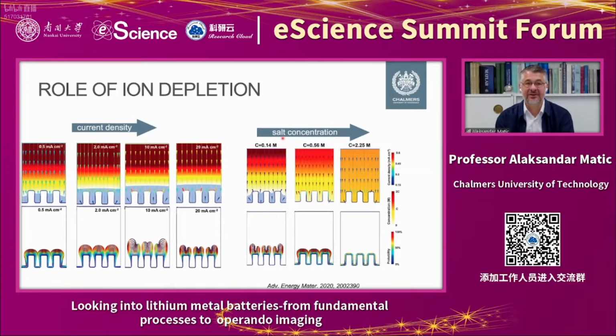The key here is what happens in a cell when you run, for instance, a large current or low temperature, basically when you have a transport limitation in a system: you get a depletion of lithium ions close to the surface. And if you have a depletion, then you will have preferential deposition on any protrusion that is formed. This is also why high salt concentration is beneficial for homogeneous deposition.